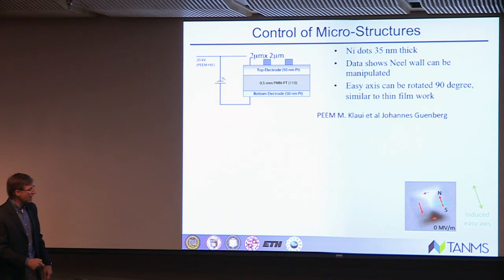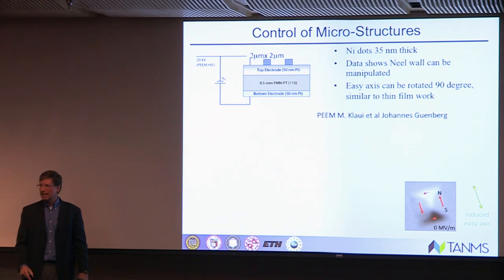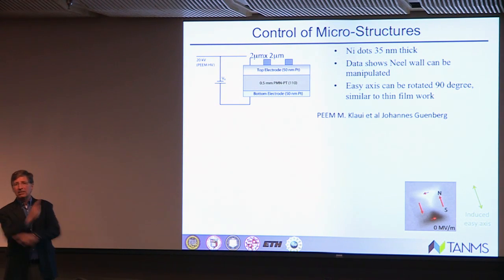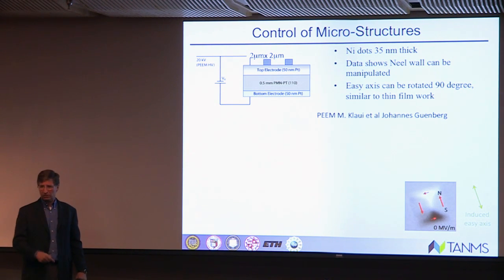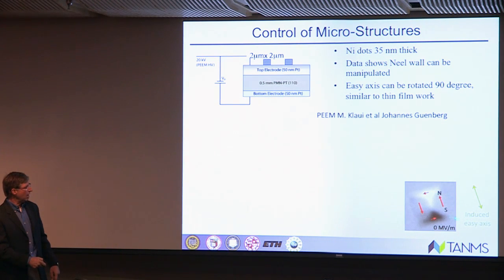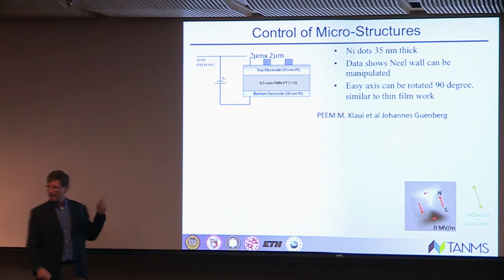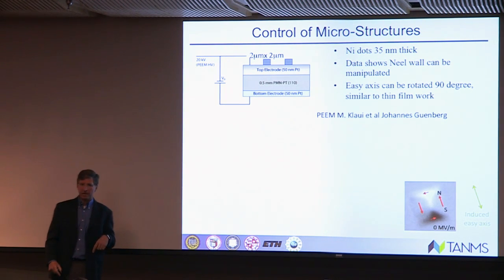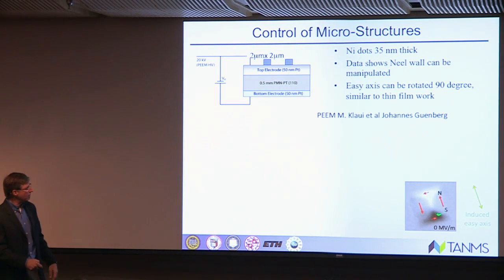Now you see these gray regions front and back? That means your domain is actually 90 degrees to your X-ray. So we have parallel, anti-parallel, and 90 degrees. So we have 4 domain structures in that 2 micron by 2 micron bit of information. Now, the other thing I need to point out, if you notice, we've drawn these arrows on these sides much larger than these. So this actually has an easy axis along this direction here.